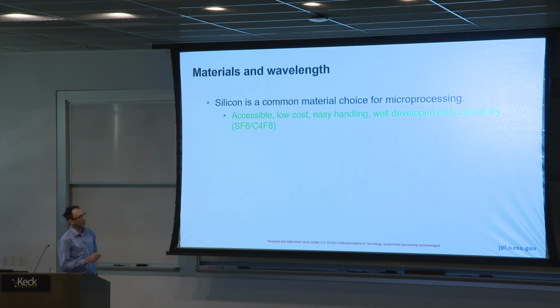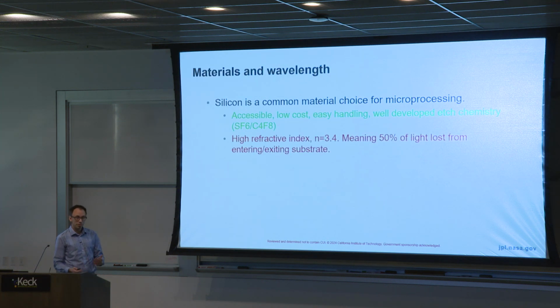So that's what I utilized in the first example where you saw these spindly-looking tall pillars. However, silicon, I mean, if silicon is so good, why don't we always use it? It does have a few notable drawbacks. For instance, it has a fairly high refractive index. If you consider a transmissive metasurface optical element, just by entering and exiting the substrate, you lose about 50% of the light just because of the Fresnel reflection at these interfaces.